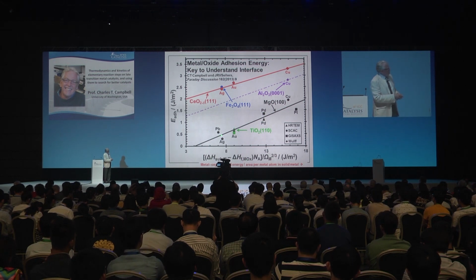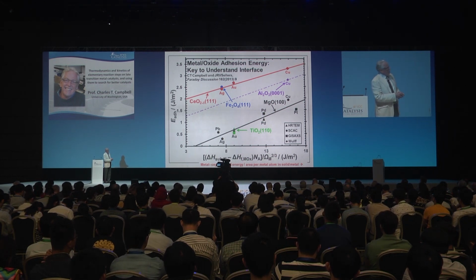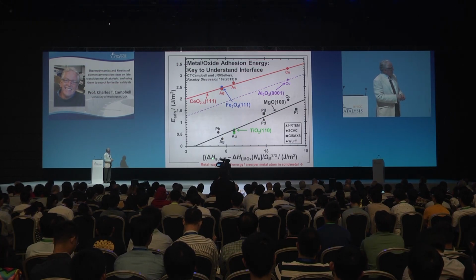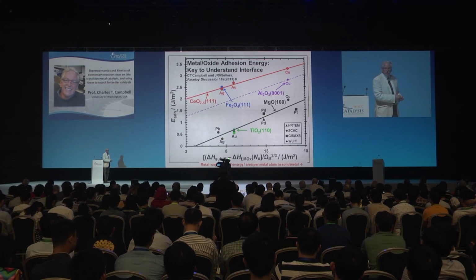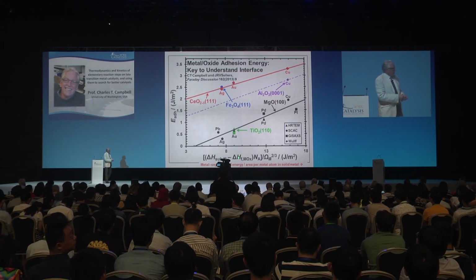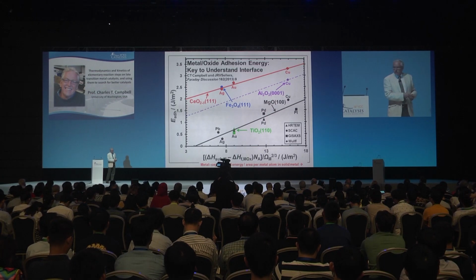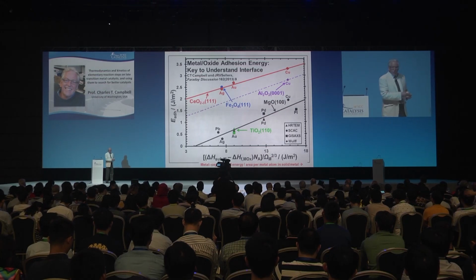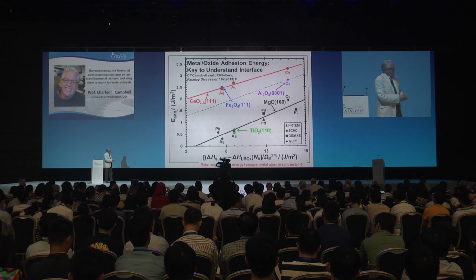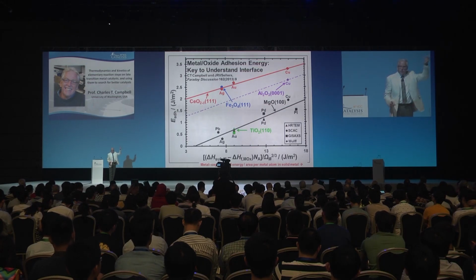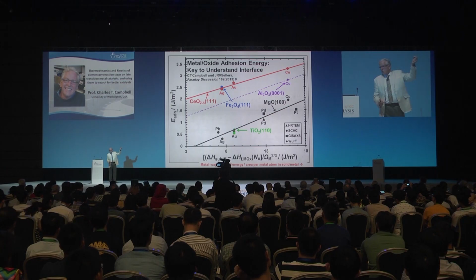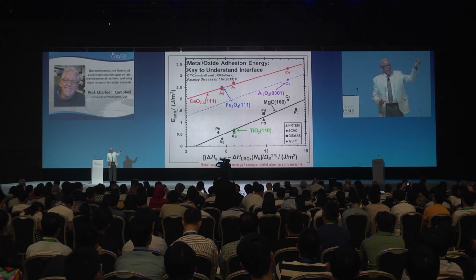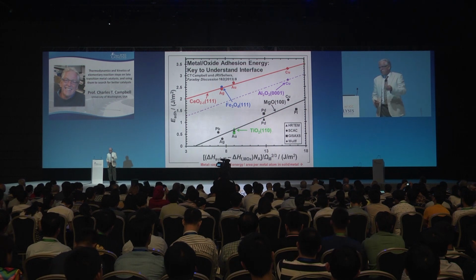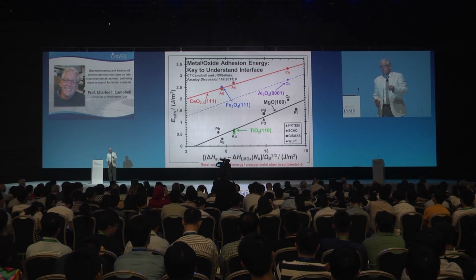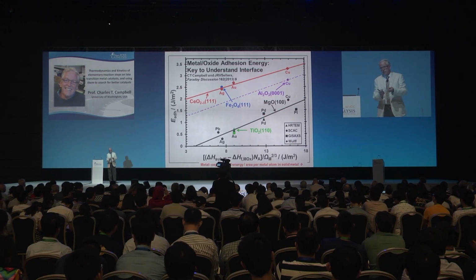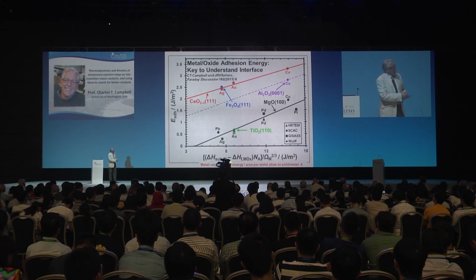And those all seem to fit on the same trend here for magnesium oxide, where this is an axis that has something to do with the nature of the metal that's supported on MgO. And this axis is the heat of sublimation of that metal in the bulk, and the heat of formation of the most stable oxide of that metal per mole of metal atoms. Basically, this is the energy difference between a gas phase metal atom plus O2 gas and a metal atom in the most stable oxide of that metal. And that means it has something to do with the strength of the metal-oxygen bond, and that this adhesion energy should correlate with that.